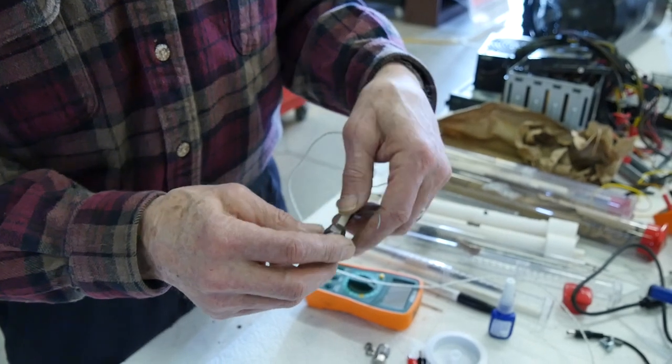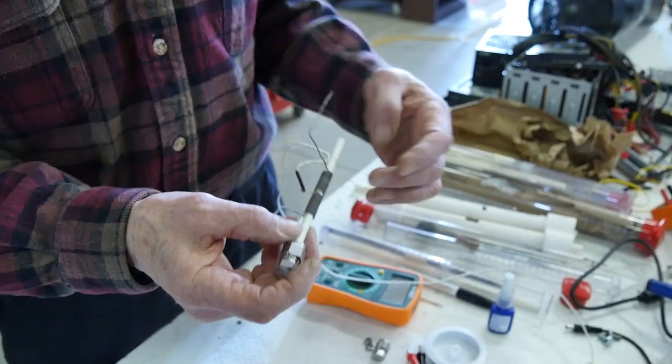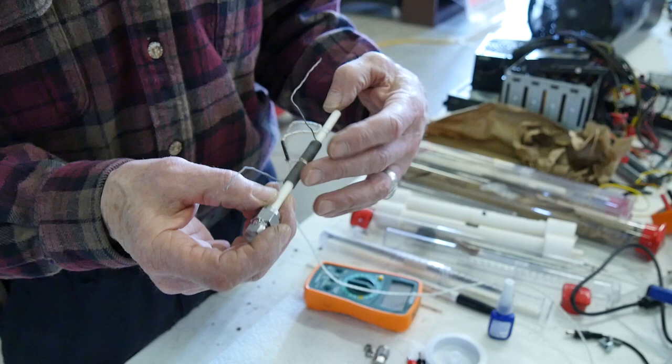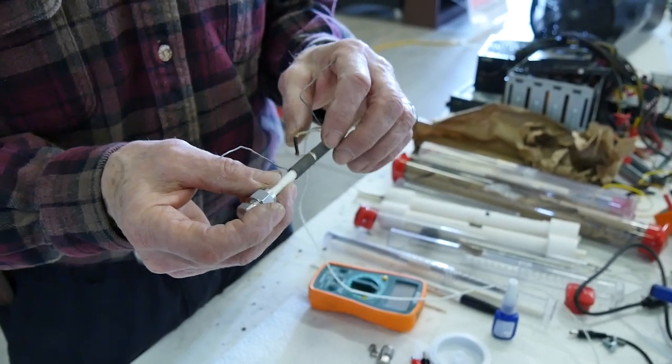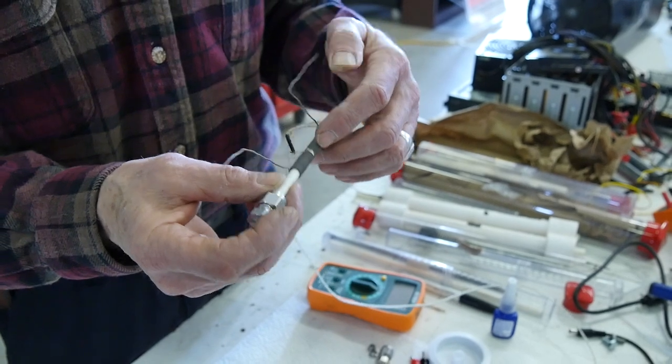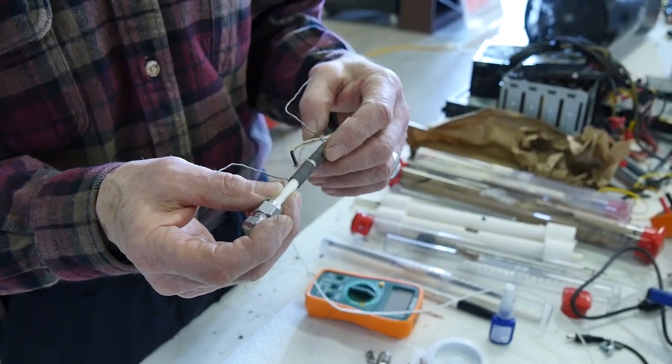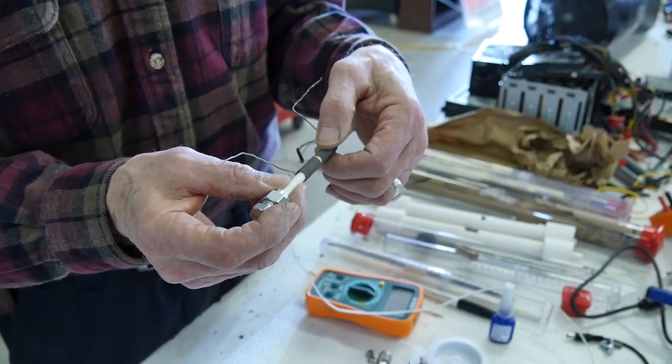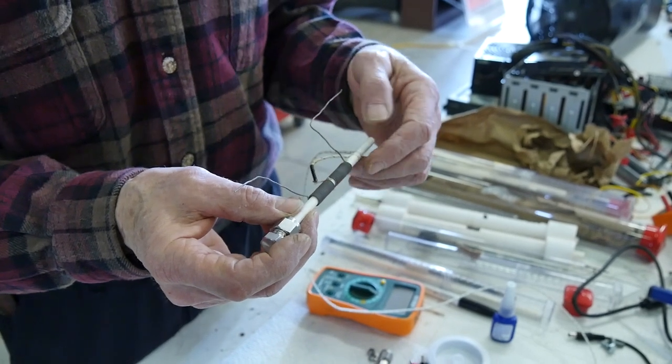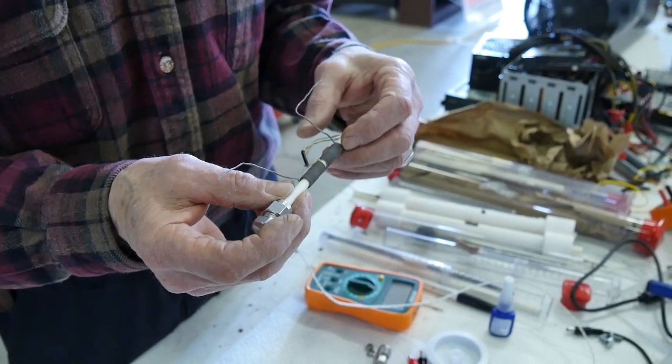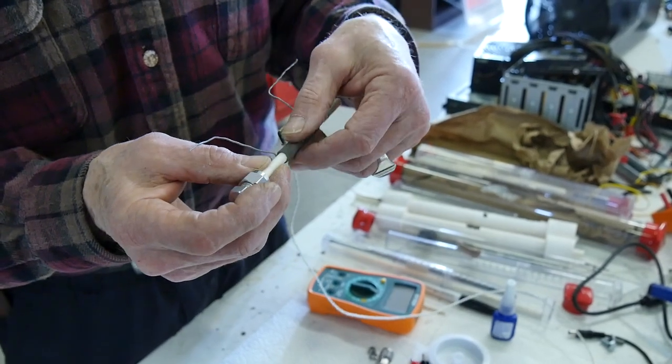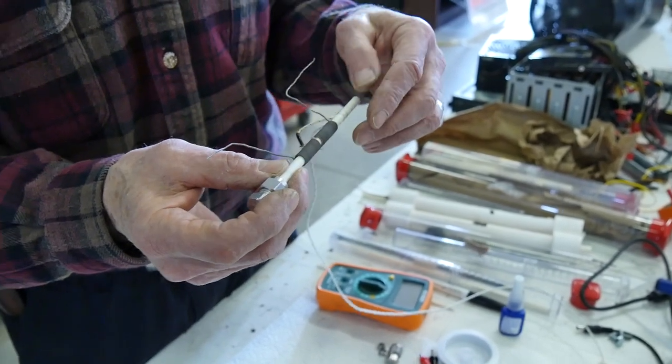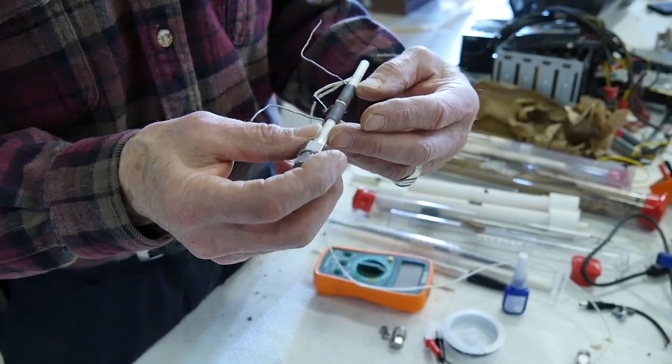So how are we going to test for that? Well, we're putting a little bit of lithium aluminum hydride mixture in the tube. We're going to seal both ends with these. We've got a little heater coil and a thermocouple, and we'll bring it up to about 250 degrees Celsius. And at that point, the LiAlH4 decomposes, the hydrogen comes out, and it builds up very high pressure inside the space here.